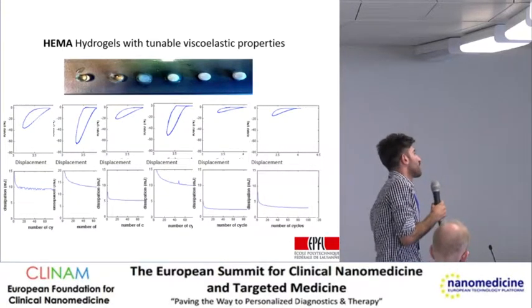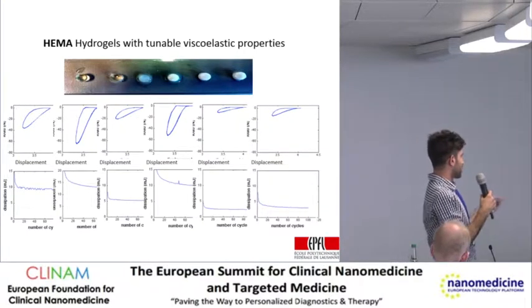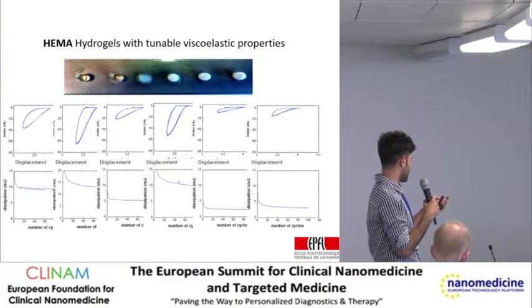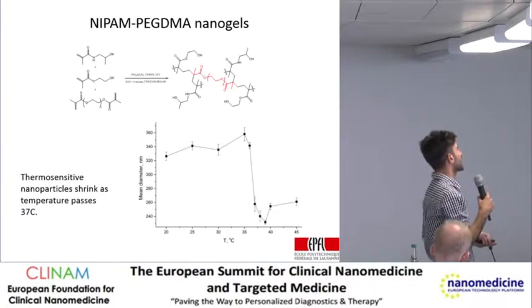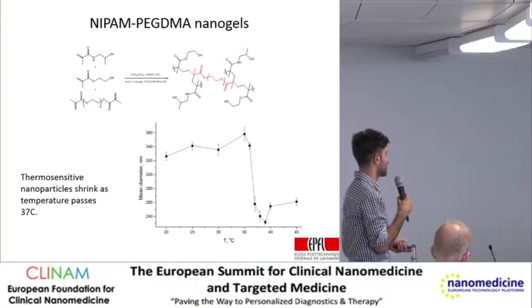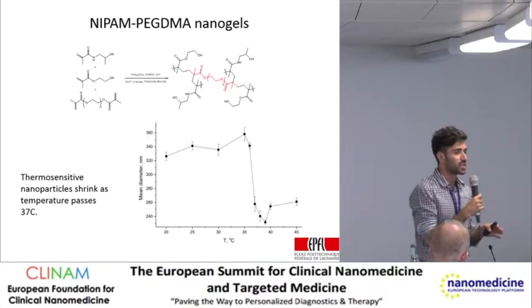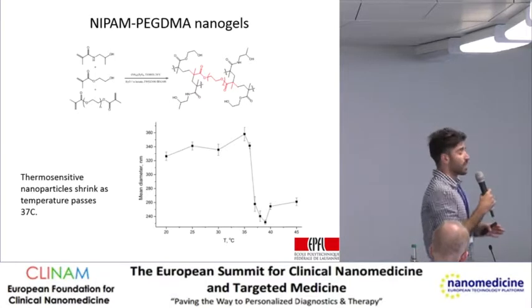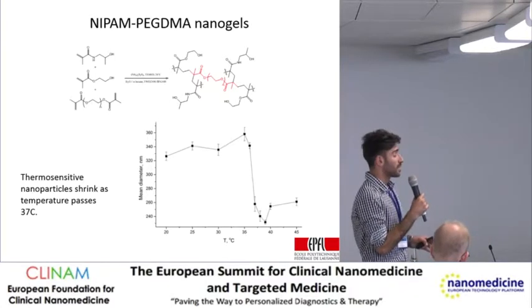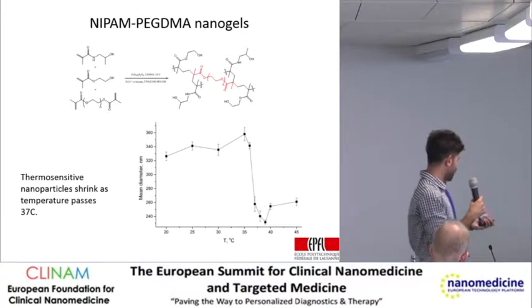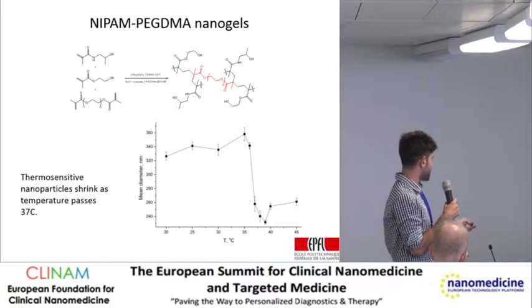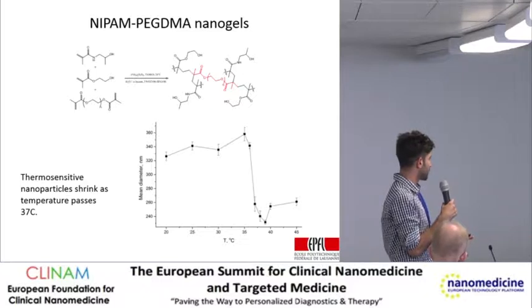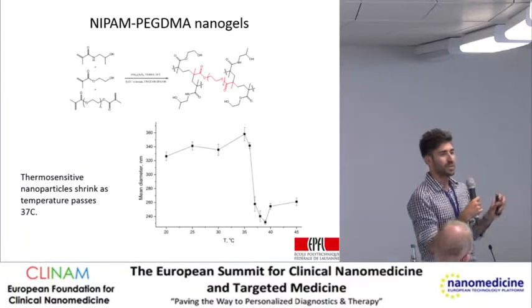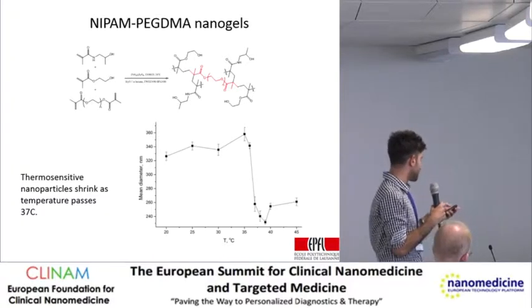We played with different parameters in this hydrogel, like crosslinkers and water ratio, and we could reach a wide range of mechanical properties. On the other hand, we had these thermosensitive nanoparticles, which were produced by room temperature inverse miniemulsion of isopropyl acrylamide, and they are designed to have a very sharp response at 37 degrees. So when the temperature changes from 36 to 37, they shrink from 340 nanometers to 240, which means that in volume they become almost half size.